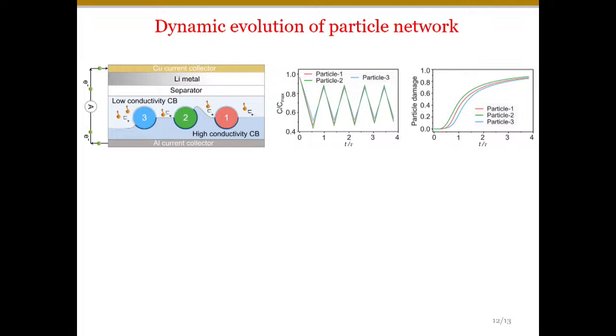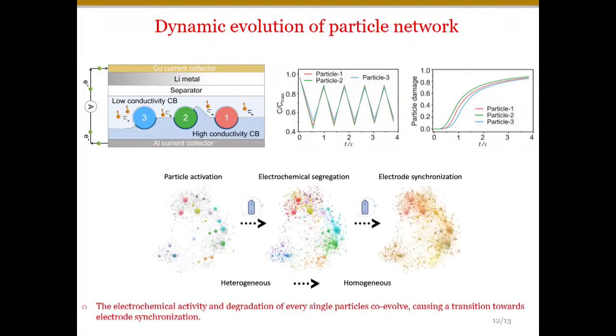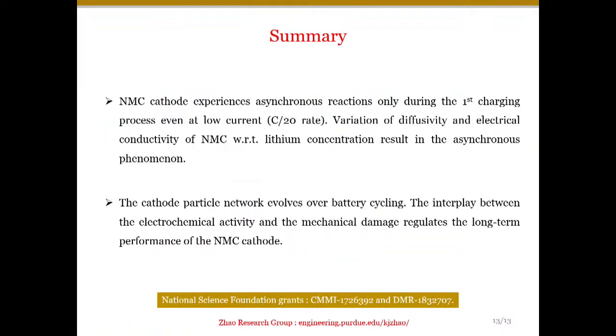During the initial cycles, for both concentration and damage, we observe a similar diverging behavior, but slowly it homogenizes. This gives us much more information about how electrochemical conditioning occurs in electrodes, and how during the initial stage after manufacturing, particles go from localized activation to more of an electrode-synchronized behavior in terms of damage.